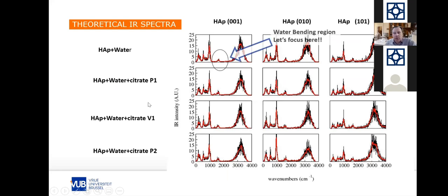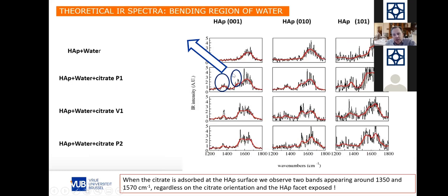Okay. So now what is important is what happens in this region. This is in fact the water bending region. I go fast, but if you take a look at it, you will see it is important. If we enlarge this, we see this thing. You see there is nothing here in the pure water. So when you have this appearing, this means there is citrate. Now the question is, if we look at the experimental data, which model will fit best to the experimental spectrum?